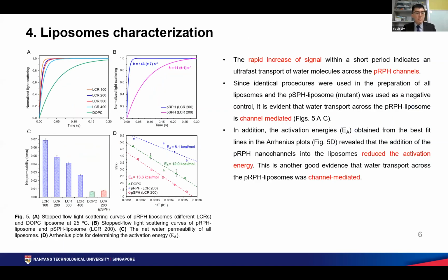Let us now take a look at the results starting from the characteristics of the liposomes. From figure 5a and figure 5b, we can see a rapid increase of light scattering signal within a short period of time for the PRPH liposomes, which is actually a good evidence of the fast water transport through the PRPH nanochannels. Because the pSPH liposome was used as a negative control, the huge difference in the initial gradient between these two curves in figure 5b shows that the water transport across the PRPH liposome is actually channel mediated.